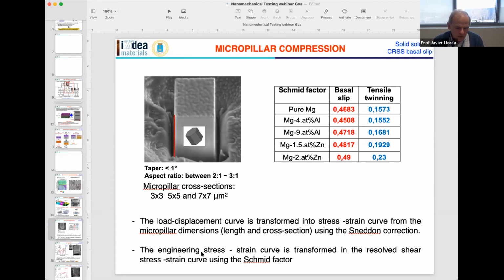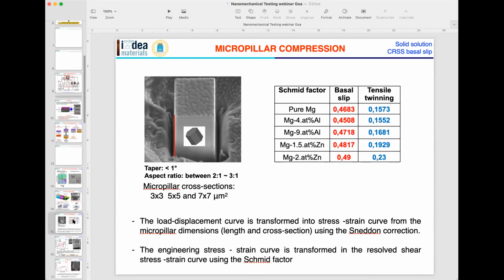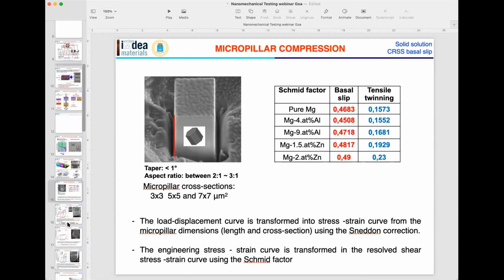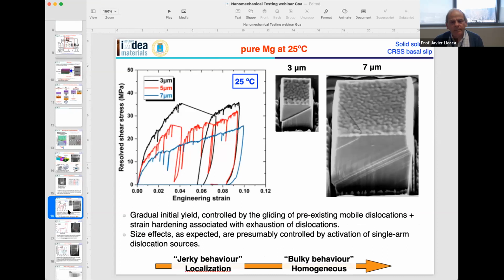And of course, when you have the engineering stress-strain curve, you can transform it into the resolved shear stress-strain curve. That's what you want to measure the critical resolved shear stress using the Schmid factor that you know for the given crystal orientation that you have here. Okay, so let's go just to one example.